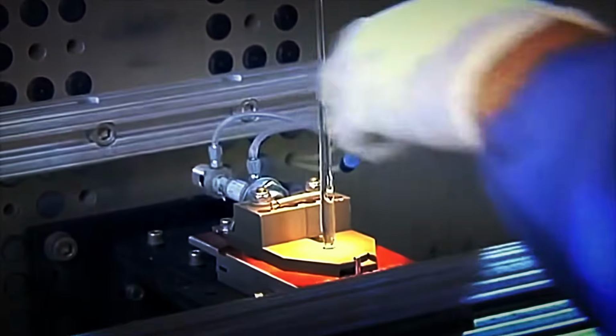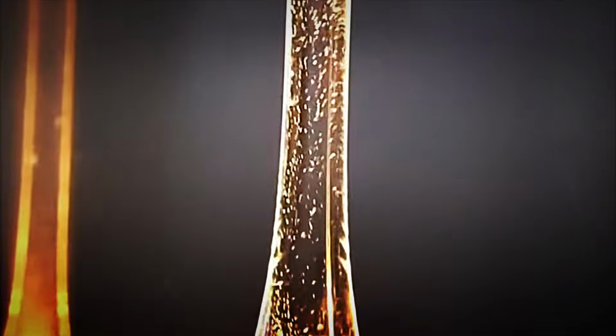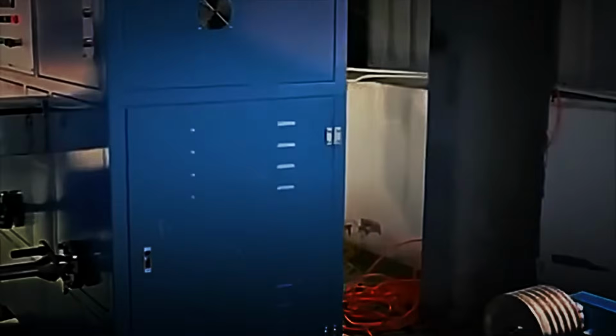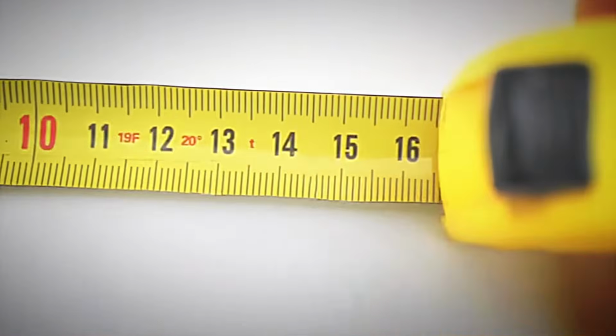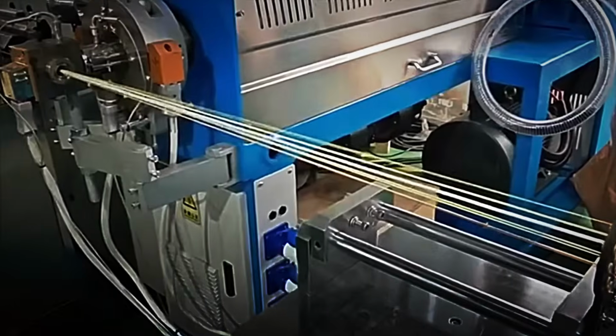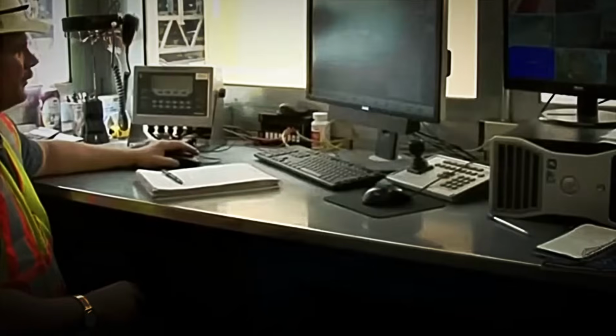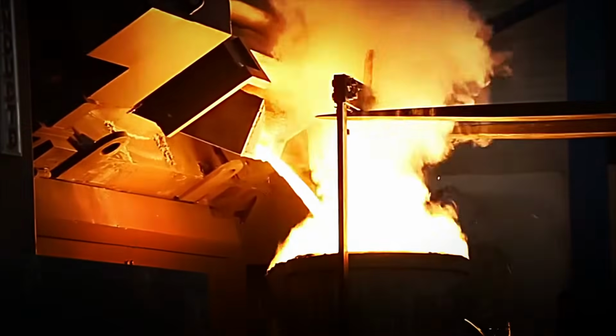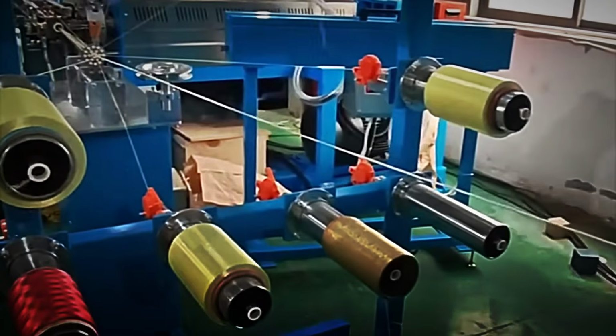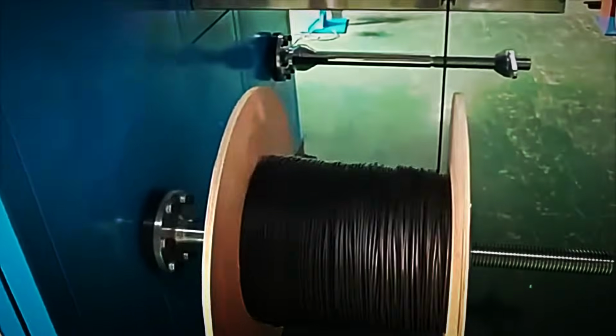At this point, the filament is so thin and fragile that any vibration could break it. The fiber is then captured by a system of guides that pull it downwards. The descent speed must remain constant. If it speeds up, the diameter decreases too much. If it slows down, the fiber thickens. Standard optical fiber has a diameter of 125 microns, equivalent to the average thickness of a human hair. To maintain this accuracy, laser sensors monitor the diameter in real time. If variations are detected, the system automatically adjusts the temperature or drawing speed. Production rates are high.